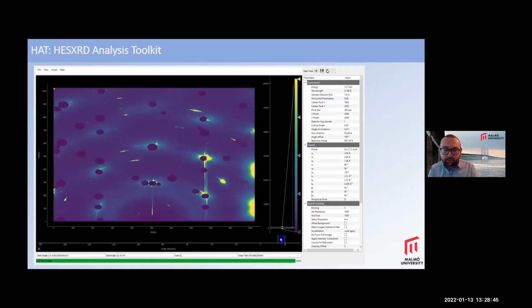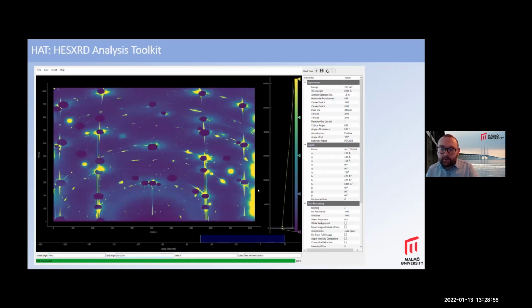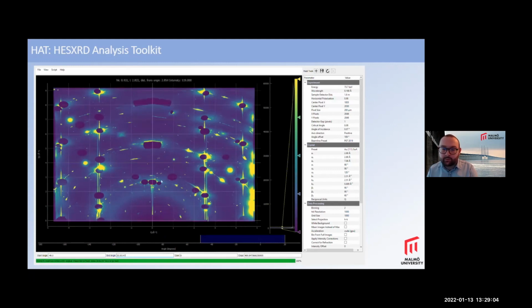You can change the color. I just set the angles back to the full range of the scan. And then we can also quickly convert this to this coordinate representation. So this corrects for the curvature of the Ewald sphere, like this. And then what we're able to do is add various masks into this.